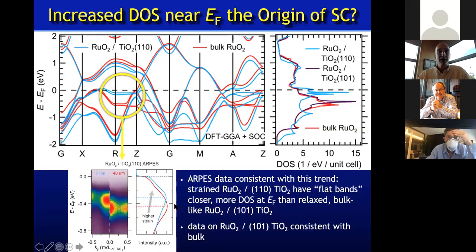My colleague Kyle Shen is able to look at by ARPES and see what is actually happening to the bands. And what he sees is that if we go from this more relaxed film to one that is more highly strained, indeed, you can see the angle integrated, there is indeed a shift in the density of states toward the Fermi level, which is consistent with what theory is pointing out here.